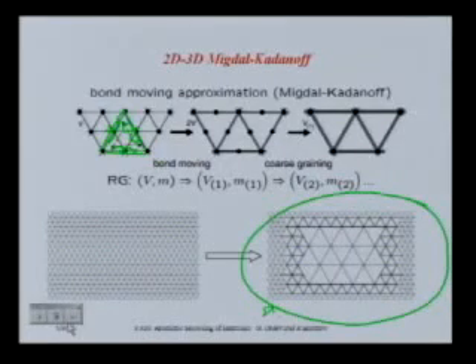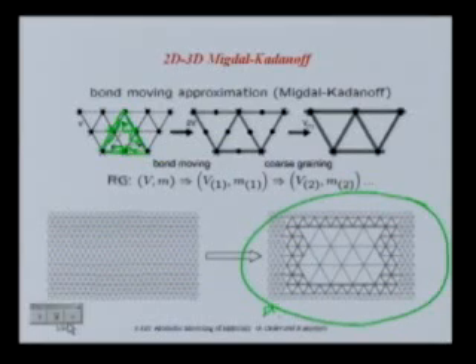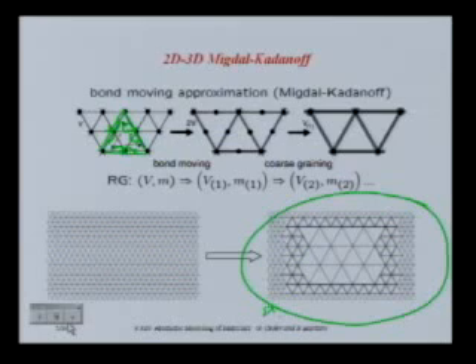So when you do something like this: if you define the potentials at a given temperature—because the renormalization of the potential depends on temperature—and you run this at any other temperature, these regions will have different thermal expansions. And so you'll build up internal strain in your system without knowing it.